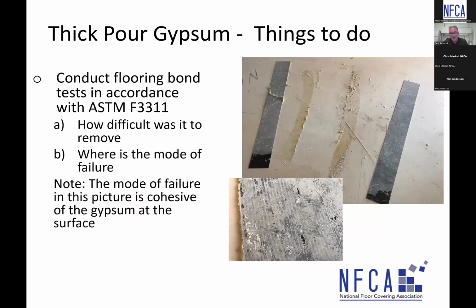We mentioned, somebody brought this up earlier. I thought I had it in here. A great practice, not just on thick pour gypsum, but really on any project, whether you're going over concrete, going over patching material, leveling material, thick pour gypsum. Most all of your flooring manufacturers will recommend conducting mat bond tests. We built an ASTM standard and released it a couple of years back, ASTM F3311.